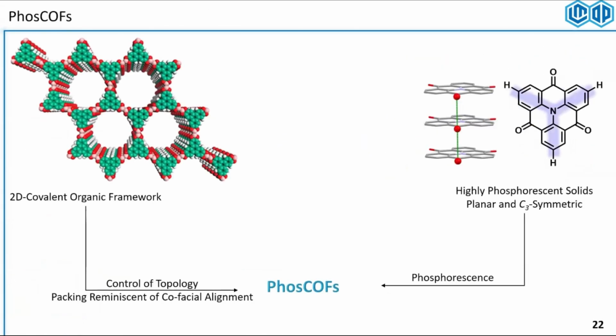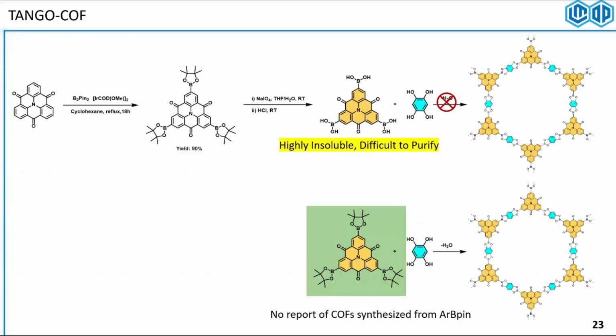I looked at the molecule we had. Tango is symmetric, planar, and we could easily think of ways to make covalent organic frameworks with it. So why not make such a COF? And because in most covalent organic frameworks, pi-pi stacking is face to face, in their crystalline phase we would expect them to be actually highly phosphorescent as well. I started making boronic acid derivative of tango to make COFs, obviously.